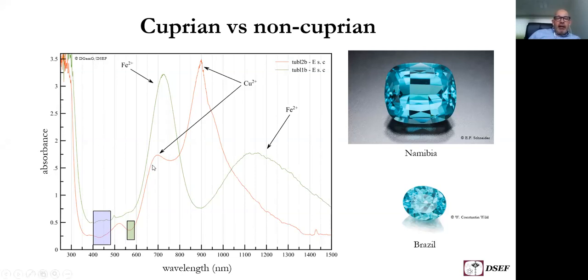If you just look at the visible part of the electromagnetic spectrum, the red is a copper tourmaline, and the green here is the iron colored tourmaline. You can see that if you look between 700 and 350 nanometers, there's not a big difference. So actually you cannot differentiate between the two with a handheld spectroscope. You have to use a spectrophotometer to detect the second copper absorption band to tell that it is the Paraiba tourmaline.